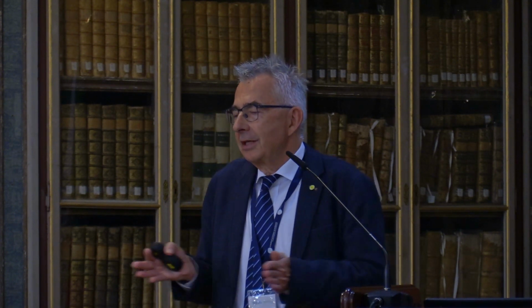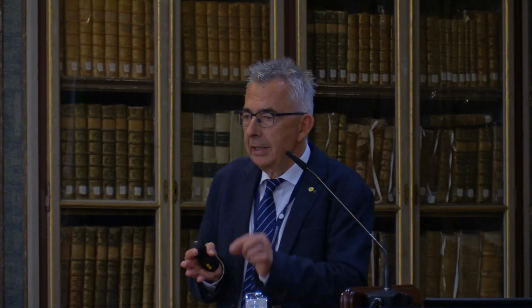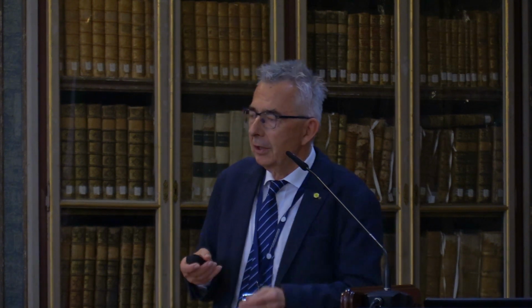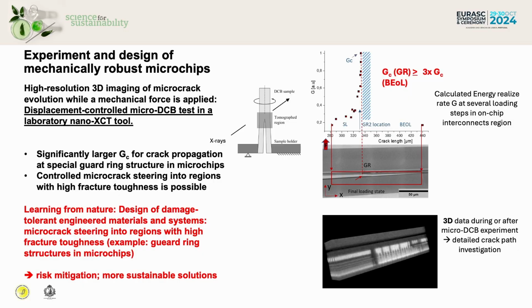Why is it now important to study further? Because it has to be as small as possible, because each micrometer of silicon costs a lot of money in microelectronics. So with this in situ experiment in the X-ray microscope, we can show that the critical energy release rate is significantly increased at the guard ring, and we have a controlled microcrack steering into regions with high fracture toughness.